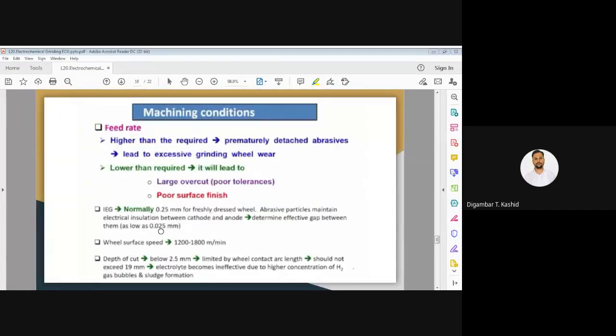Now another point, the machining condition. If you give a feed rate higher than the required one, then prematurely detached abrasive particles will be there, and it may lead to excessive grinding. And if you give a lower feed rate than required, it will lead to a larger overcut, that means poor tolerance, and it may give poor surface finish. If you provide a low feed rate, that time also you will not get the proper surface finish. So we have to give the optimal feed rate.